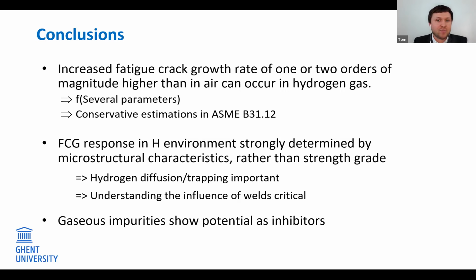A lot of studies state that the susceptibility to hydrogen embrittlement increases as the material strength increases. However, other authors conclude that the fatigue crack growth response in a hydrogen environment is determined by the pipeline steel and its specific microstructure, rather than its strength grade. Moreover, over the years, different types of pipeline steel grades, produced following different production processes, were implemented in the network as well. Attention should be given to the welded connections as well, given their variety of microstructures.